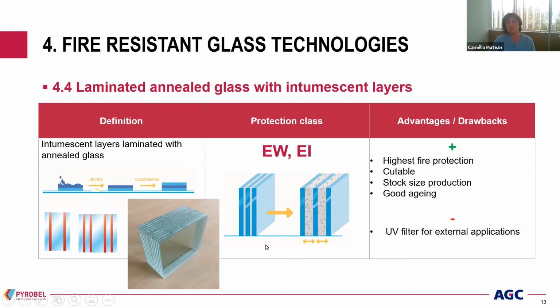And how does this glass work in case of fire? The intumescent interlayer contains a limited quantity of water, and when the temperature on the glass increases to over 100 degrees, this water starts to boil, which activates the foaming of the layer. This evaporation or boiling of water is an endothermic reaction which will absorb the heat and will cool down the glass. And with the foaming, the interlayer will turn into an opaque and resistant fire barrier.